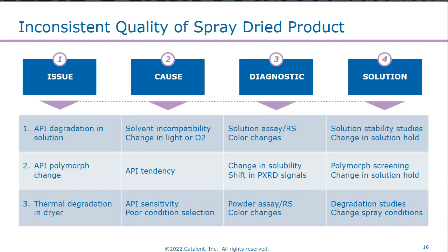Some ways to address this are really formal solution stability studies. These should be performed throughout product development as we change scales and change the time and conditions we're holding our solution in. Another thing that's often useful to consider for late phase development is changing the way you hold your solution, perhaps looking at holding the solution at 2 to 8C versus room temperature, particularly if you anticipate long spray drying times and need to be covered against potentially weeks of API in the solution state.